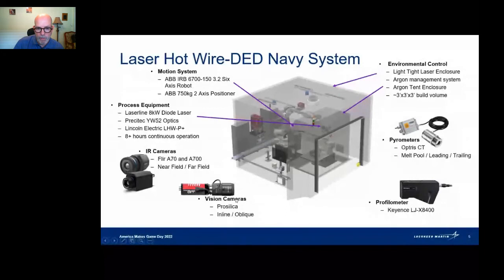One is mounted inline with the travel direction of the robot itself, and the other is an oblique camera that's kind of off to the side. Both are grabbing images of the melt pool itself. Finally, we've got 3 different pyrometers. One is a melt pool pyrometer that is, again, measuring the thermal conditions at the melt pool. And then we've got leading and trailing pyrometers just ahead of and behind that melt pool as it travels.